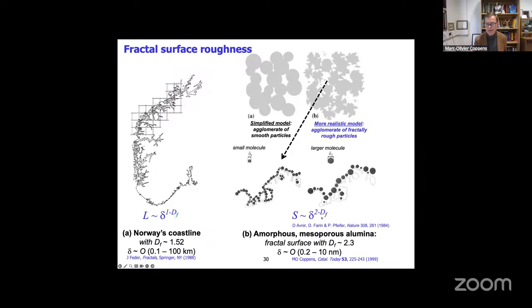and you also have a fractal scaling law, where the fractal dimension now is a number between 2 and 3. For a coastline it would be between 1 and 2. So if it's 2, it would be smooth. 3, it would be a volume filling surface, right? And both happen, and you can have everything in between. There's a bit of a cartoon here of what you have for a porous alumina based on all these aggregates, but they actually are rough. And so this is a much more realistic model, and we should see how we account for this.